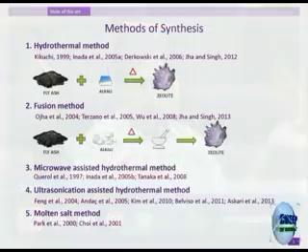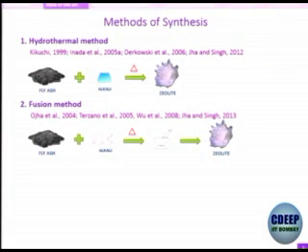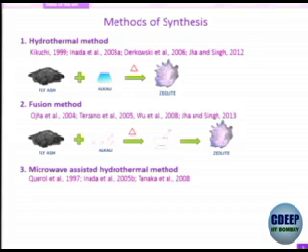So if you can synthesize the whole thing, you get at least 100 rupees per kg from 0 rupees per kg. So there are various ways in which you can synthesize zeolites from fly ash. Basically, the typical method is the one that I told you about. It's called the hydrothermal method. The other method... We have patented all these methods. So in case you need our help, I will charge you, but I will give you the technology. So you can treat the fly ash with an alkali and fuse it at high temperature, 550 degrees or 600 degrees, and then you can synthesize zeolites out of it. Another way is treatment with microwave radiation.